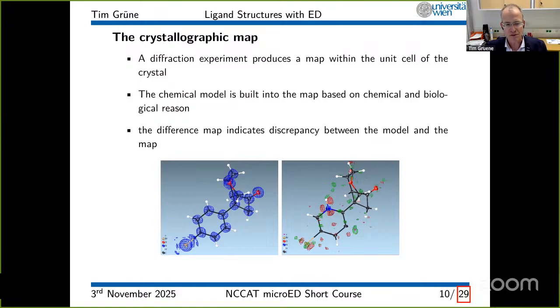For small molecule structure, the resolution is not the most important part. As a chemical crystallographer in X-ray crystallography, you're taught that you need 0.8 angstrom resolution because then your data to parameter ratio is better than 10. For small molecules, 0.9 to 1 angstrom is sufficient, which is a resolution that many powderish samples at least diffract to. And then you can start making changes. In my experience, the difference between oxygen and carbon often stands out even with electron diffraction data when they look shabby, as long as the resolution is high and the multiplicity should be high. So we always merge data from quite a large number of crystals, 5 to 10, because the merging of these data sets helps a lot to stabilize basically the data quality.